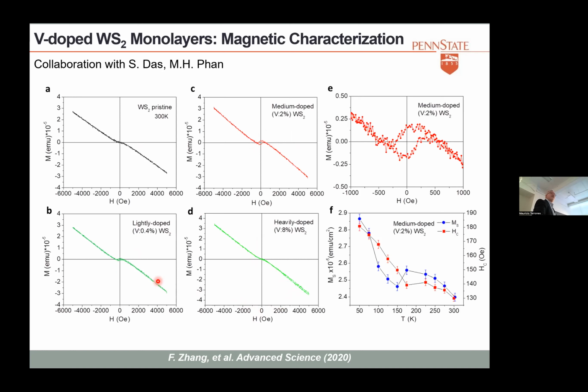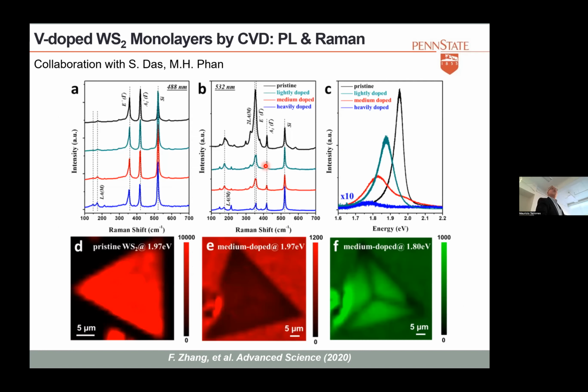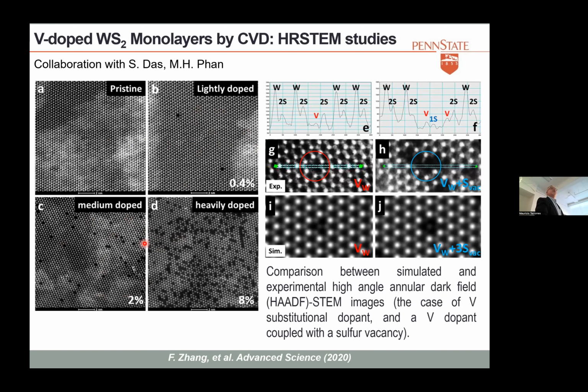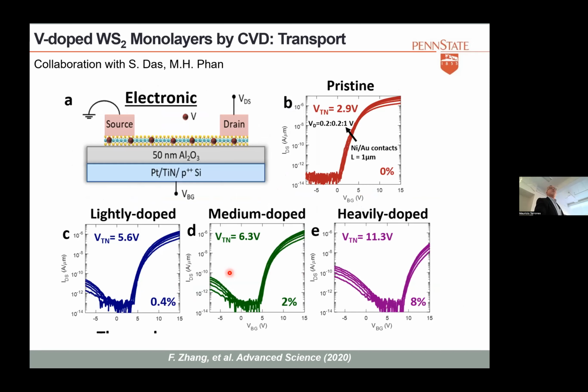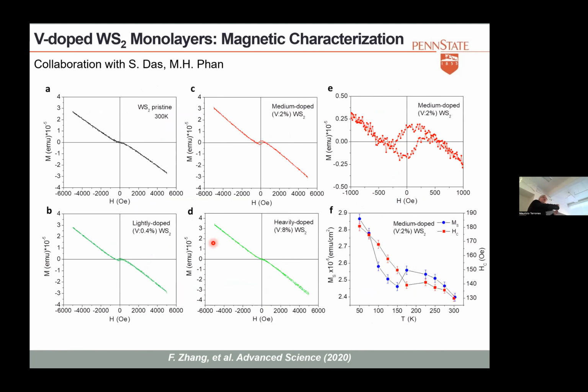So you remember the average space in between the vanadium at 2% was around 1 to 2 nanometers. So the interesting case was here, but also this is interesting when you have this clustering of vanadium atoms. We could see ferromagnetism, and then we didn't see any ferromagnetism, and this was interesting. This is at room temperature, with coercive fields around 130 oersteds in this case, and at a lower temperature we have a bit higher, right?